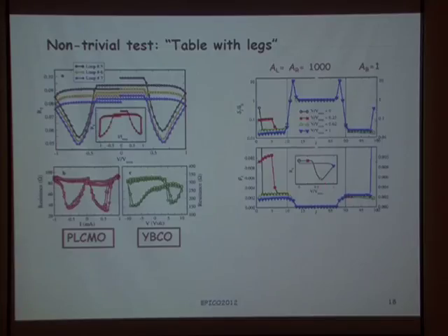Of course, when we change the polarity, we can repeat the same arguments, but injecting vacancies instead of taking vacancies away from the interface. So when we inject vacancies, we again increase vacancies, increase resistance at both interfaces, and the total resistance increases.